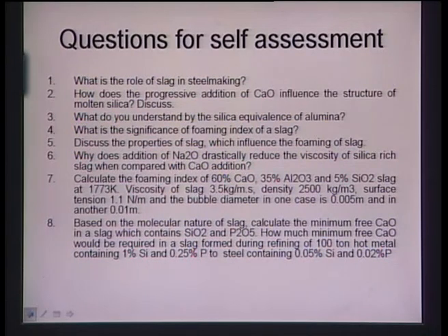Why does addition of Na2O drastically reduce the viscosity of silica-rich slag when compared with calcium oxide addition? This I have already explained, because Na2O is a single charge. Now, calculate the foaming index. Though I calculated for you, you can again recalculate, and also you can procure different slags, find out the different properties, and categorize the slag with reference to the foaming index.